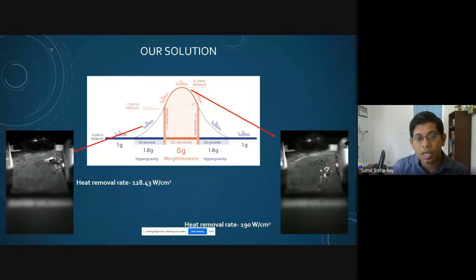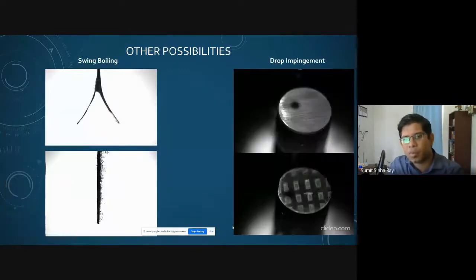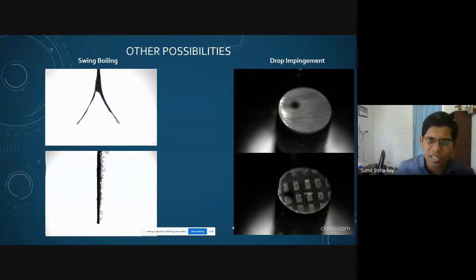In ground condition, we could remove all the way up to 600 watt per centimeter square. In zero gravity condition, we could remove about 190 watt per centimeter square, and that is one of the highest data that has been obtained for zero gravity conditions also. So this is what we did during our experiment. Now the question is, what else can be there? There are many other things that can be studied. This is what we have been trying to do at IIT Mandi in our lab.